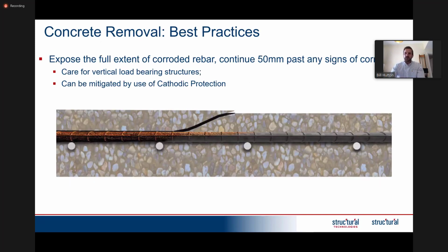Something else which is extremely important is to make sure that when you're excavating the concrete, you not only remove the concrete which is delaminated or spoiled, but you extend that chipping until you reach a length of clean steel. The reason for that is that if you only remove the loose concrete and you leave steel in place which already has corrosion product on it, which would mean that the concrete's already contaminated, then around the outside of that repair, you're definitely going to see a premature failure.